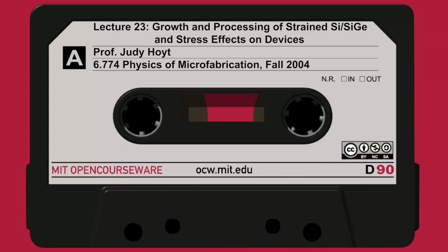Now, maybe it wasn't such a great idea to put that much stress and use polysilicon. It wasn't necessarily a practical thing, but it shows that, depending on how you do your processes, how you do your STI, it can have a pretty big effect, particularly on the hole mobility. So this was an early indicator that people need to pay dramatic attention to exactly what thermal budget you use, what materials you use in STI, in every layer you put on that device. Now that the devices are small, the width of devices today is less than a micron, edge effects can have a huge impact on the stress in the center of the channel, and that can end up impacting the mobility.